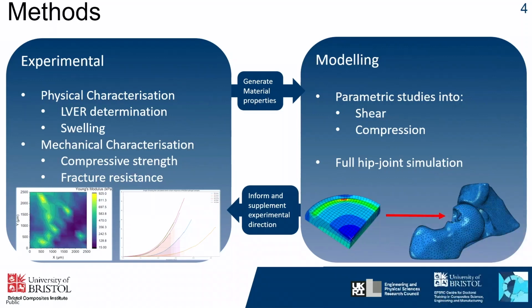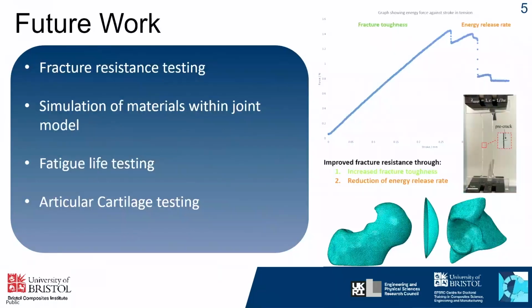These material properties can then feed into the modelling, and so I can generate hyperelastic material models that can then be tested, and so I've reconstructed a hip joint from CT scans within Abaqus, and then I will insert the models into the joint to test their material properties and run parametric studies. And again, so this informs the experimental direction to move that forward.